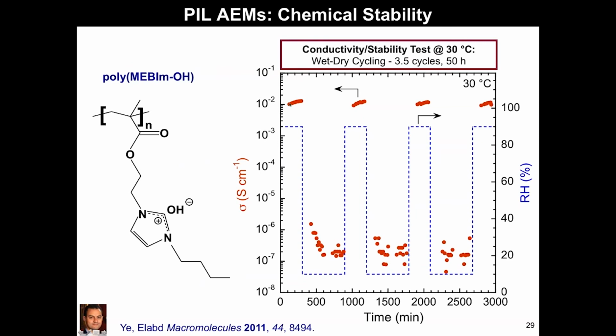So we're showing conductivity as a function of time in the red data, and we're showing our condition change from 90% over time to 10%. So you see the conductivity drops, but then over many, many hours we can recover that conductivity because remember, this is a water-assisted process. For an ammonium-based chemistry, you wouldn't be able to recover this conductivity. So this demonstrates stability under hydration cycles.